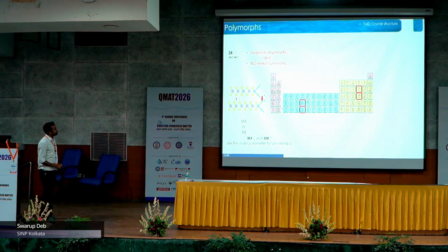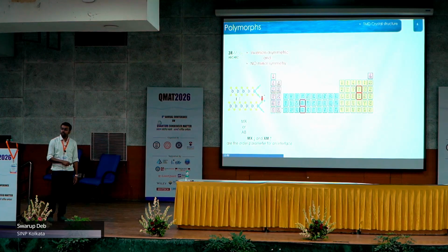Why it matters is because the chalcogen, sulfur or selenium, has much higher electron affinity compared to these metals, moly and tungsten. As a result, in this particular stacking order, that I named MX, that is metal eclipsed by X, also known as AB, the top layer would gather some of the electrons. So the top layer would become slightly negative and the bottom layer would remain slightly positive. And this is the origin of a permanent dipole moment, or a spontaneous dipole moment.